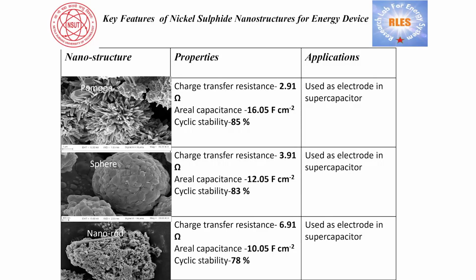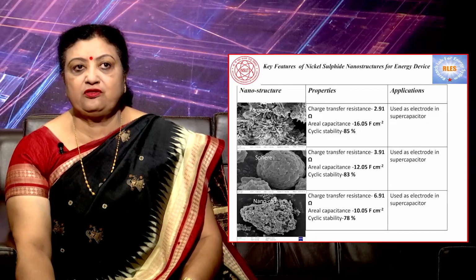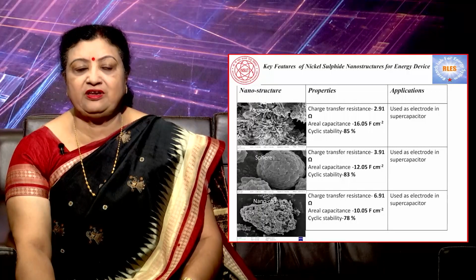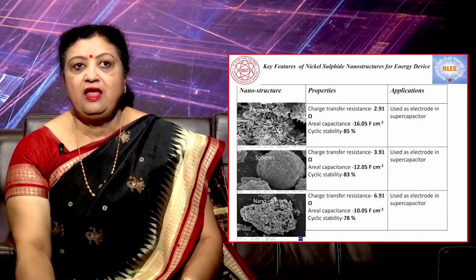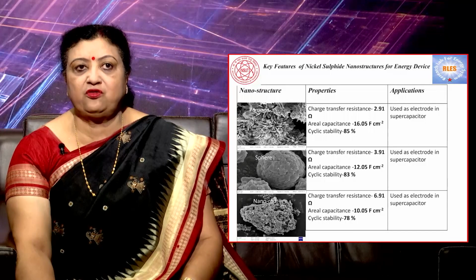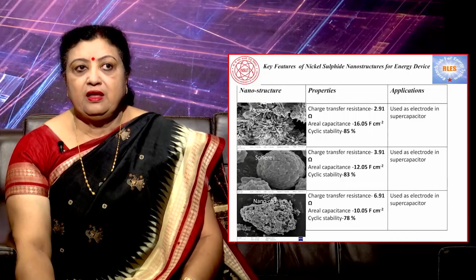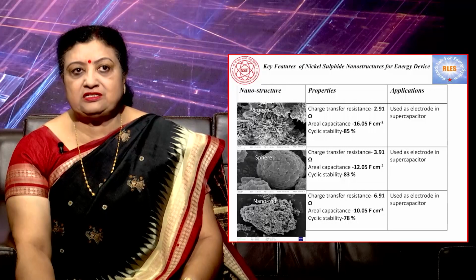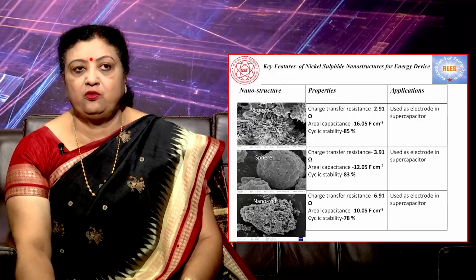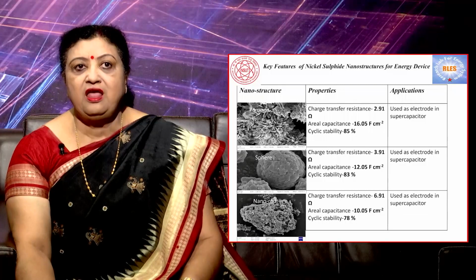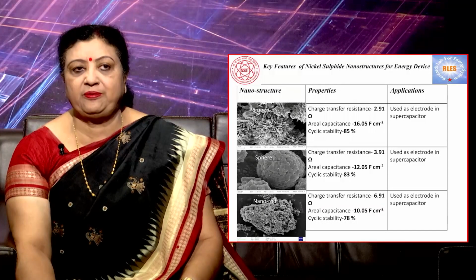Other nanostructures like pompon: the charge transfer resistance is 2.91 ohm, areal capacitance is 16.05 farad per centimeter square, cyclic stability is about 85%, and this can be used as electrodes in supercapacitor. The sphere: the charge transfer resistance is 3.91 ohm, areal capacitance is 12.05 farad per centimeter square, cyclic stability is 83% and used as electrode in the supercapacitor.